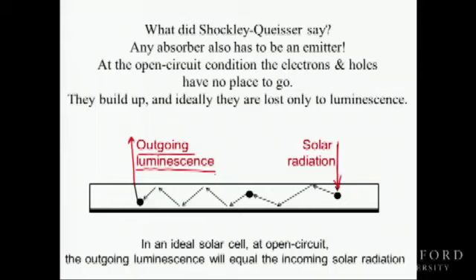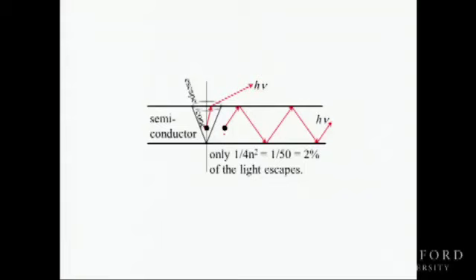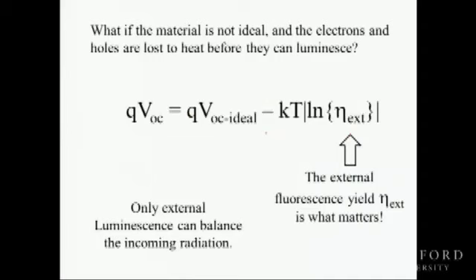You cannot dismiss luminescence. It's not a loss mechanism because it is imposed upon you by the laws of thermodynamics, the laws of radiation. If you can absorb, you must emit. Okay, and so the luminescence is inherent and unavoidable and not a loss mechanism. However, in trying to achieve what Shockley wants us to do, which is to get all the light coming back at you, coming back at the sun, we have a problem. The escape cone is only 2%, and 98% of the light is trapped internally. This is very bad.